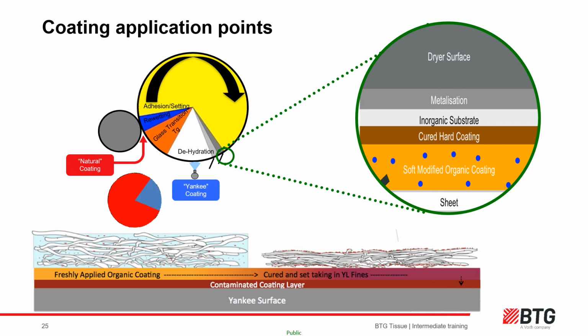Once the blade starts contacting this hard cured layer, it starts to bounce along rather than glide in the soft layer. Sheet defects such as picking or holes follow, as can breaks, especially at the edges where the web is more prone to breaks. Worse still, the blade can dig into the coating, maybe through the coating, leading to chatter in the coating, or worse still, the Yankee surface, which should be avoided at all costs. It is therefore important that the controllable and deliberately applied Yankee coating dominates over the less controllable hard cured coating layer, while still maintaining a sufficient cured coating layer to protect the Yankee cylinder.